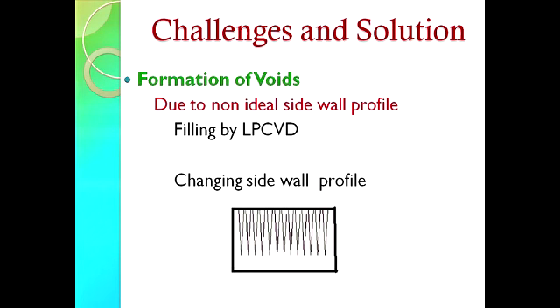So the problems that were faced in this method was the formation of voids. This was due to the non-ideal sidewall profile. Though we use deep reactive ion etching, there are possibilities that the walls are not perfectly straight, so that can cause deformation, and the pillars are not properly oxidized.